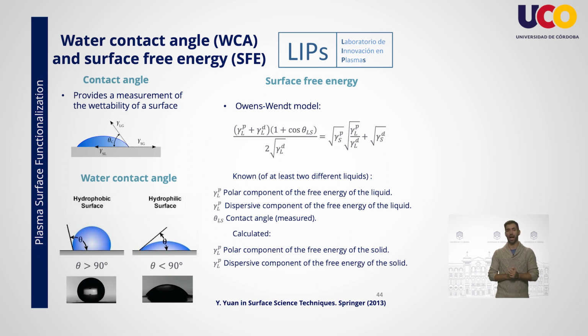On the other side, a low contact angle refers to a high chemical affinity and a high or even sometimes a complete degree of wetting. We are often interested in water contact angle measurements. These kind of measurements can be performed after taking different photographs of droplets deposited on the surface. When the water contact angle is greater than 90 degrees, we say that the surface is hydrophobic, while if the angle is less than 90 degrees, it has a hydrophilic behavior.